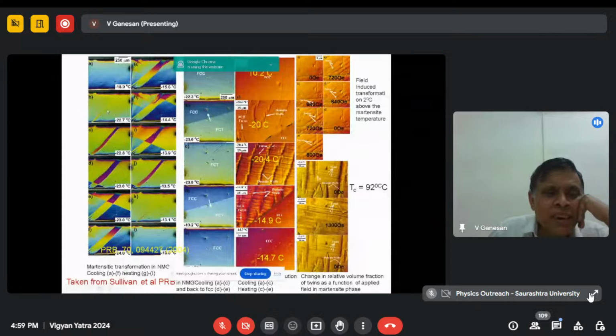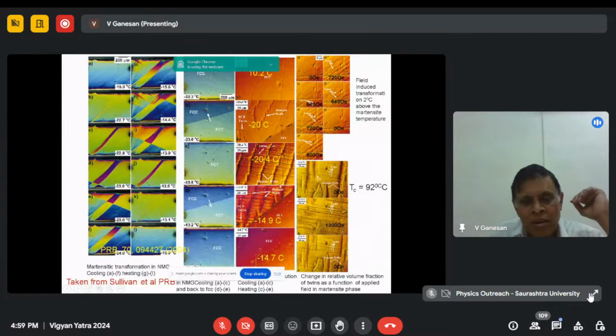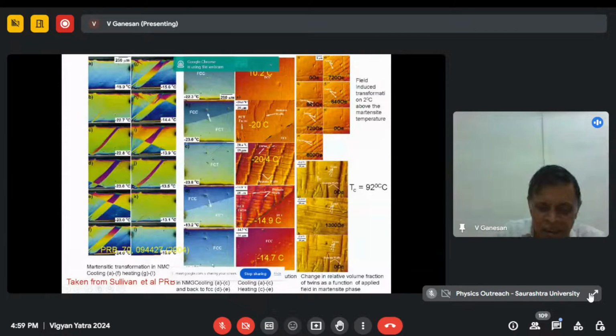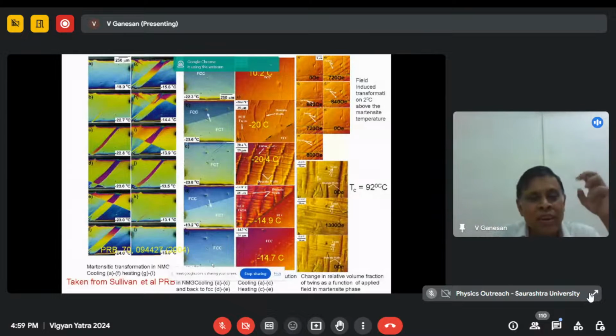So you can see that this small streak here, the streak becomes more, and finally they become 180-degree domains and then go. So this domain formation along the cubic to tetragonal transition is very famous. There are subdomains of that in the magnetism. So you can see all these things in an optical microscope by decorating with nanoparticles of cobalt. This is a very famous work of Sullivan, who is very famous for showing the magnetism at optical scales. In earlier versions of the Kittel book, the cover page shows you the magnetic domains, especially vortices of a superconductor, by putting iron particles on it. That's how they discovered the vortices, also proving Abrikosov, at very low temperature.